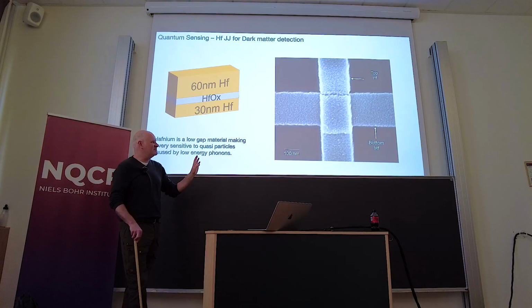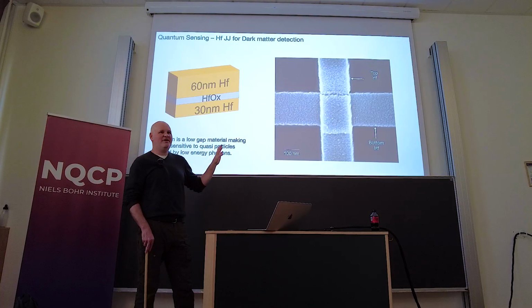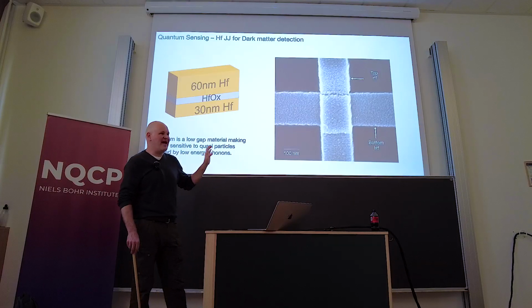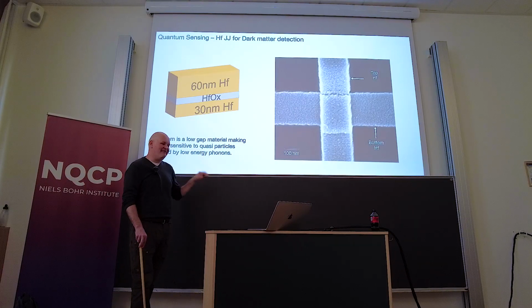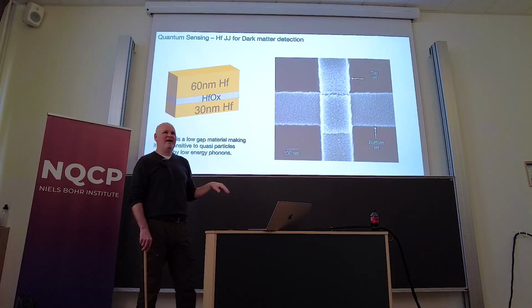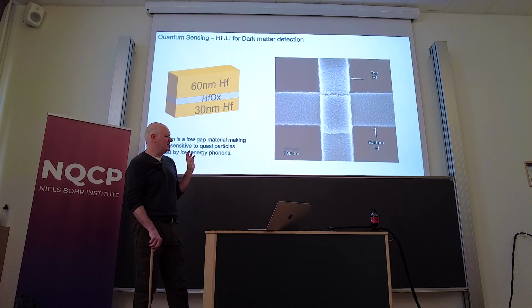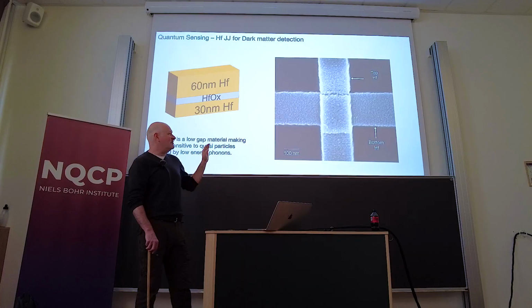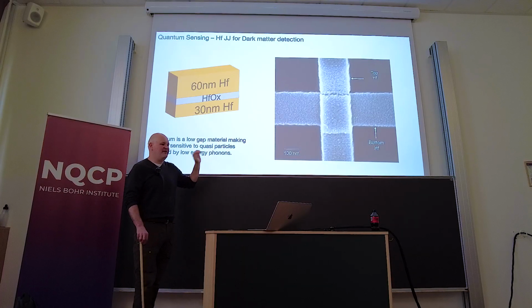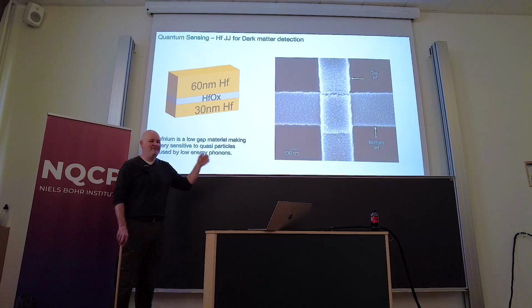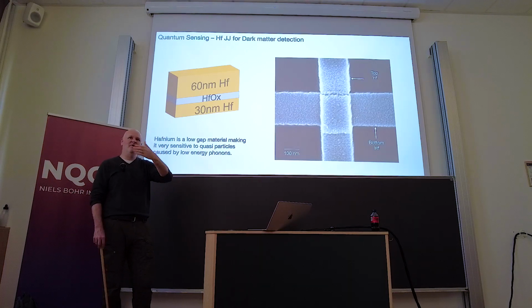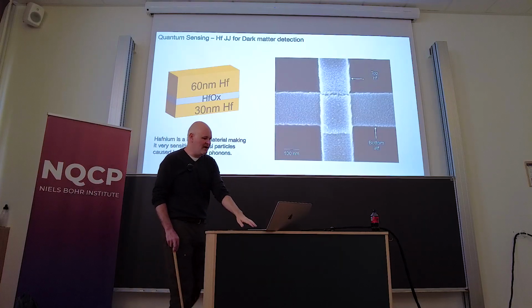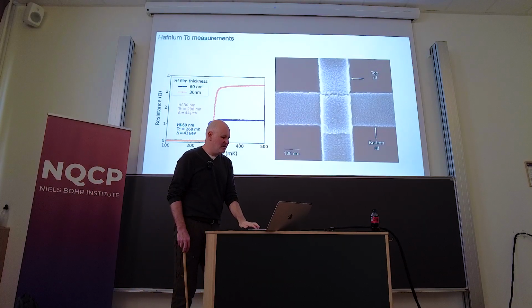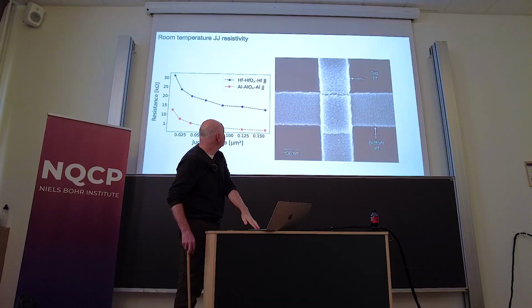So what we did is we essentially did the exact same thing that we do for aluminum Josephson junctions, but with hafnium. So we put hafnium into our e-beam evaporator, which is not the best way to make hafnium materials, but with some optimization of the growth of the hafnium and optimization of the oxidation of the hafnium, because we're doing this in the exact same way where we deposit one layer, oxidize, deposit the second layer, we were able to make it work. I'm going to skip this because I don't think it's important.